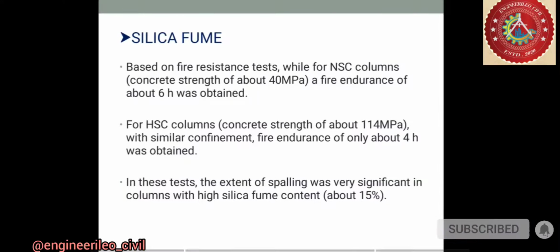The higher the silica fume content and associated compressive strength, the greater the extent of spalling, which leads to decreased fire endurance. This could be attributed to the fact that the addition of silica fume appears to reduce permeability of the concrete, restricting loss of moisture during curing, drying and fire test.